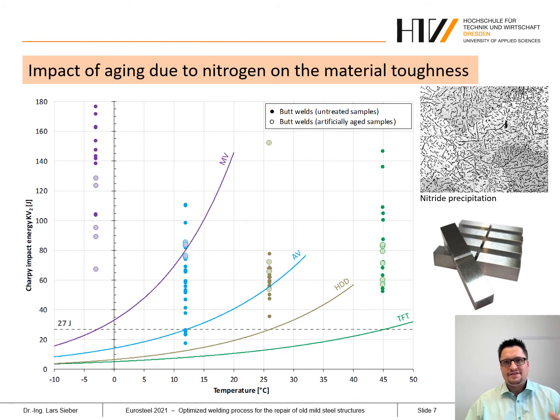In order to assess this effect, we use artificially aged samples, which means they are heated to 250 degrees Celsius over an hour, and we fabricated from the heat affected zone of these samples new Charpy impact specimens and analyzed them. This you can see here in this diagram. Obviously, the average toughness of all these analyzed samples decreases due to the artificial aging, but it is still significantly higher than in the unaffected base material.